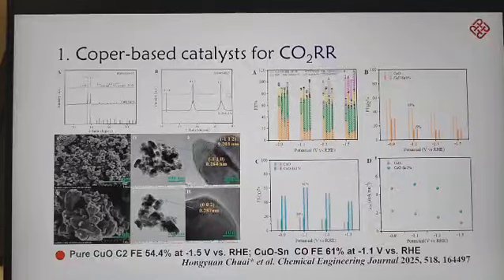In the first part of our work, in order to obtain C2 products with higher selectivity, we studied and analyzed the active sites for C1 and C2 products on copper-based catalysts. We prepared pure copper oxide and tin-modified copper oxide nanoparticles using a simple solvothermal method.